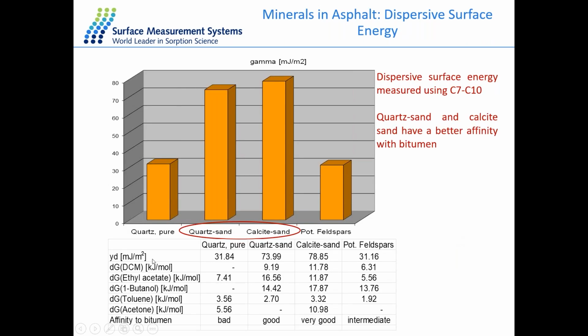So having a look at our gamma D, which is our dispersive surface energy, we've measured this using a different variety of alkanes, starting from heptane and going on to decane. What we can understand is that for our material, which has a good affinity with bitumen, we have a higher dispersive surface energy. This experiment is a very good indicator of whether our material is going to have a very high affinity with bitumen. And we can see that our two materials here have a very high dispersive surface energy.